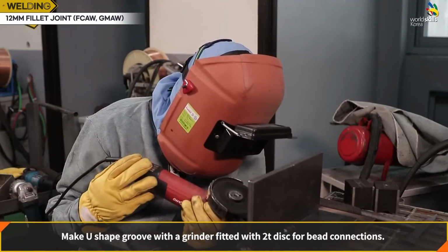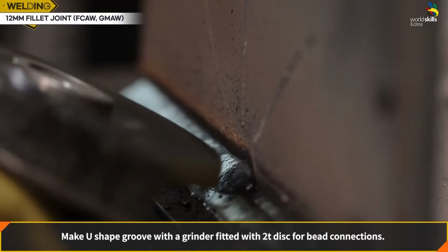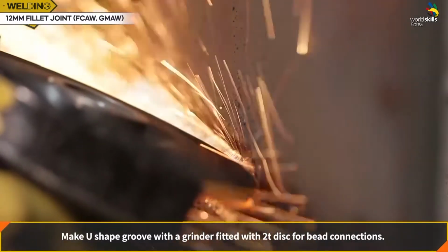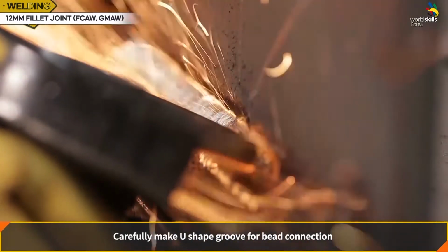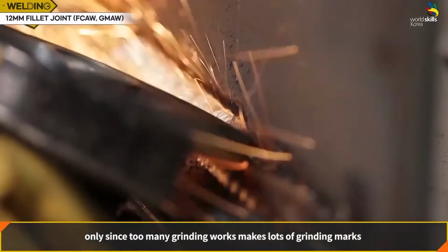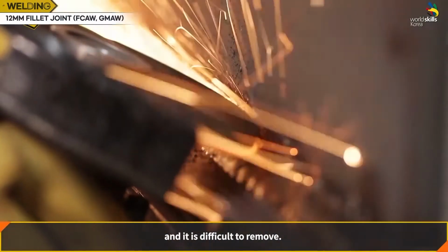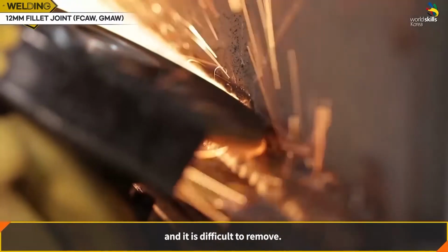Make a U-shaped groove with a grinder fitted with 2t disc for bead connections. Carefully make the U-shaped groove for bead connection only, since too much grinding makes lots of grinding marks and they are difficult to remove.